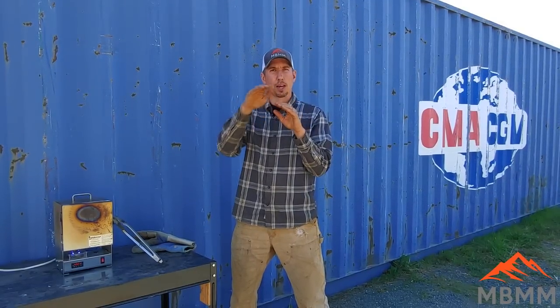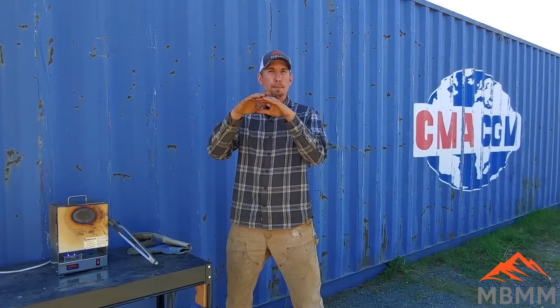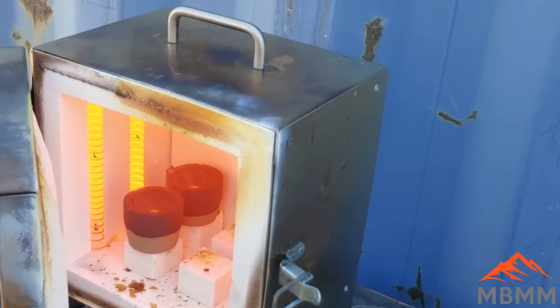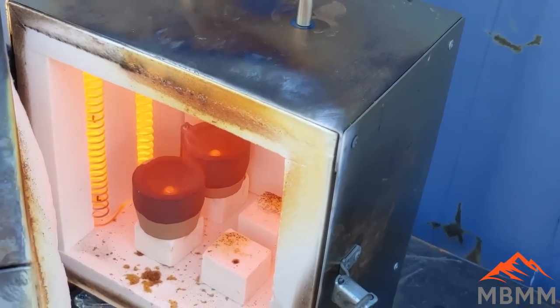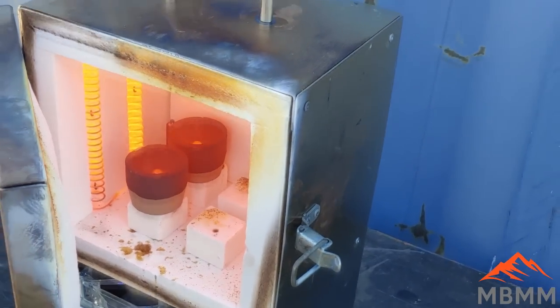But that lead metal button is impervious to the cupel, so it constantly forms an oxide layer on top of this molten lead button. The oxides are shed, absorbed by the cupel, and that process repeats until your lead button shrinks all the way down to a little precious metal bead in the bottom of your cupel. A huge percent of the button by weight is lead. But if you have any iron in there, a little bit of copper, arsenic, or bismuth, those will all oxidize as well, and the lead oxide sheds those off into the cupel as well.